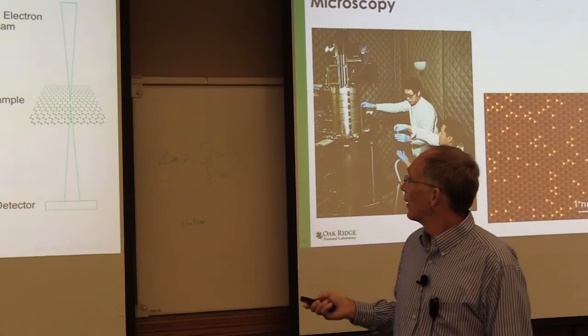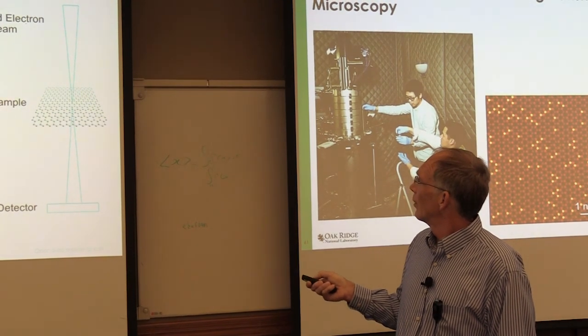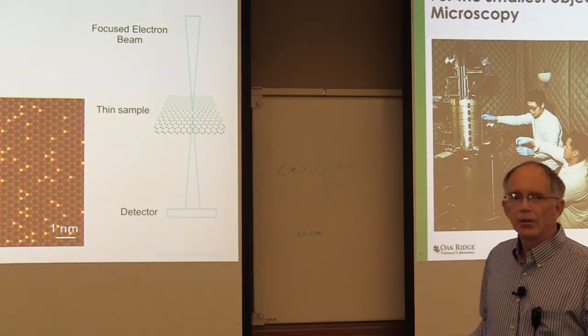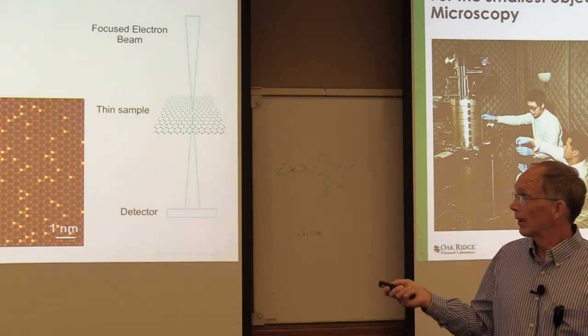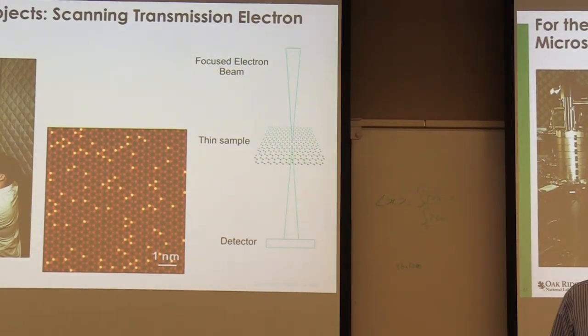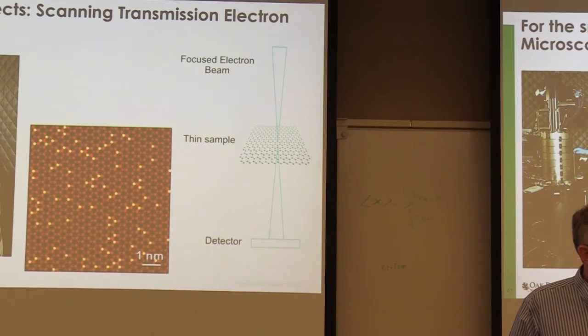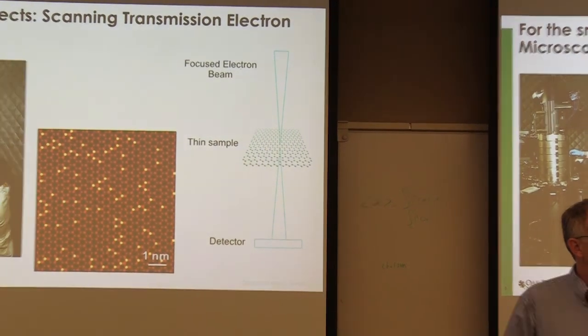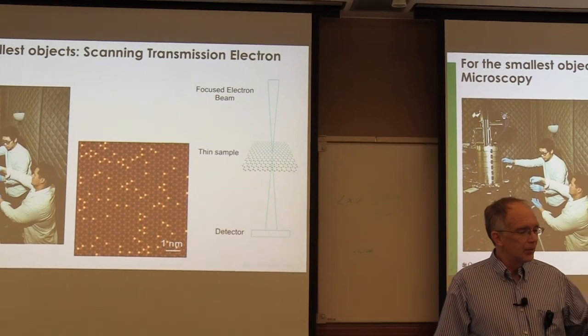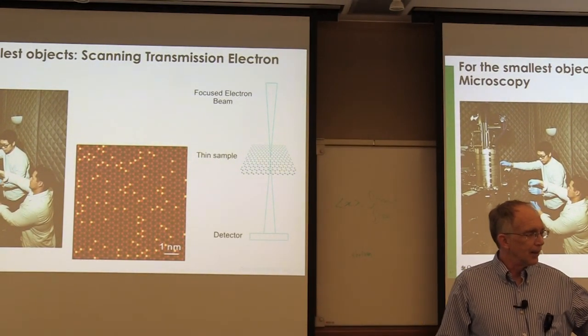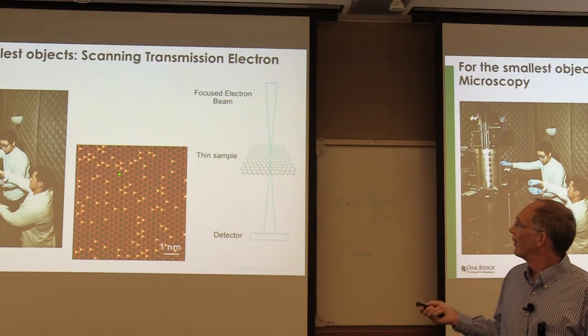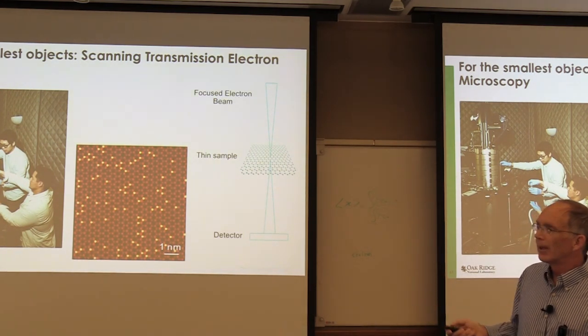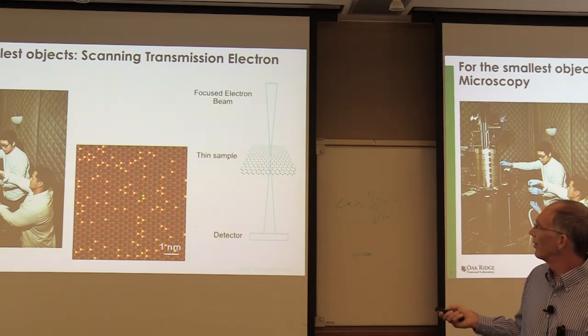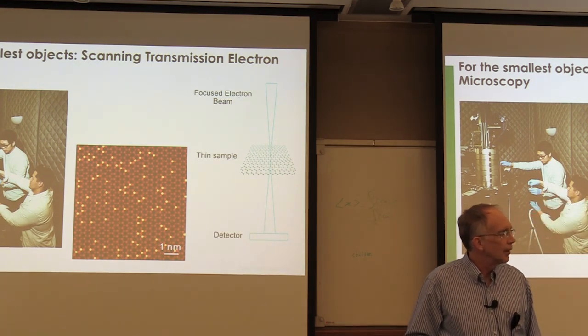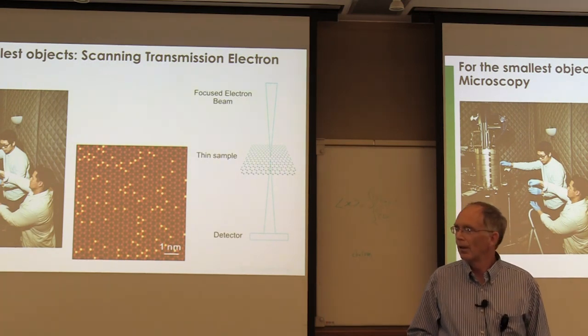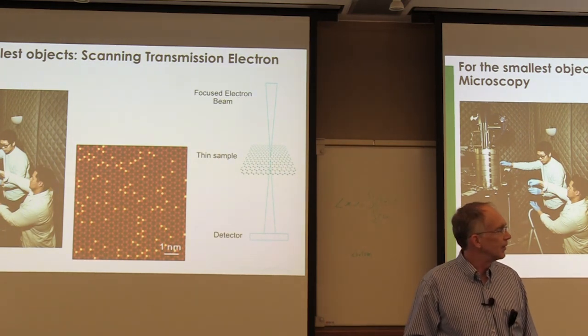So what can you do? You can put graphene in it. You can image graphene. You say, what's this stuff? Well, this is a Z contrast electron microscope. These are actual real electron microscopes right over here. It's a 100 kilovolt electron microscope that has aberration correction and Z contrast. Z contrast is the Z of the element, so it's proportional to Z. The higher the element number, the atomic number, the brighter. This is actually some silicon contamination on the surface, so they're brighter. So not only can you see where the atoms are, you can actually know what the atoms are also. Now that's pretty cool. So now we're getting to the ballgame, right?